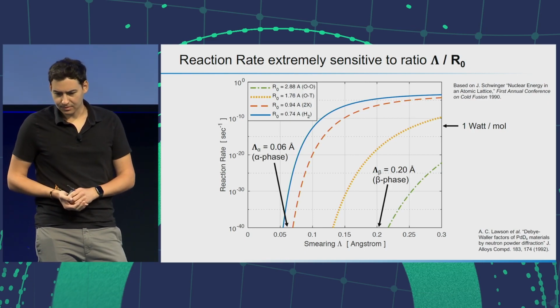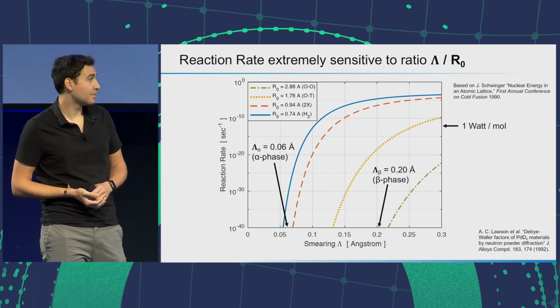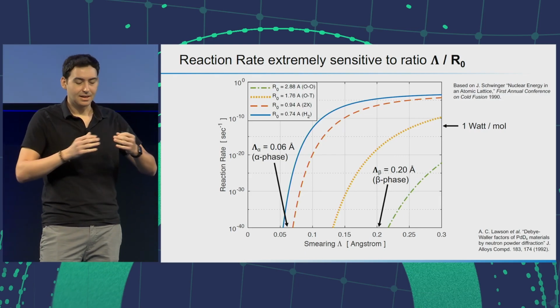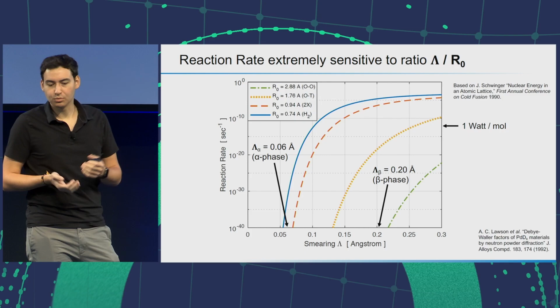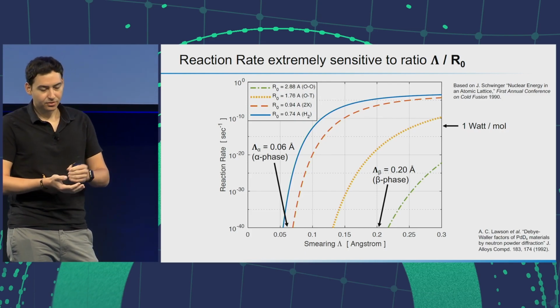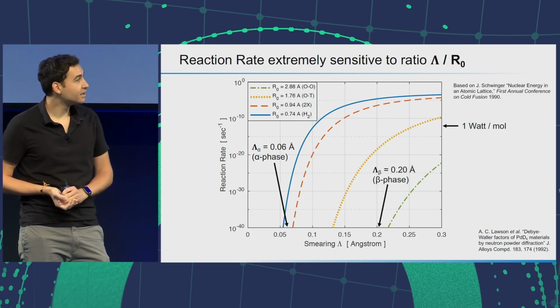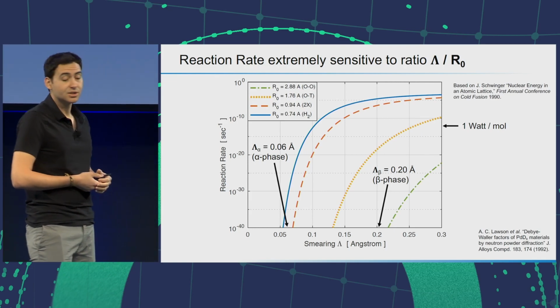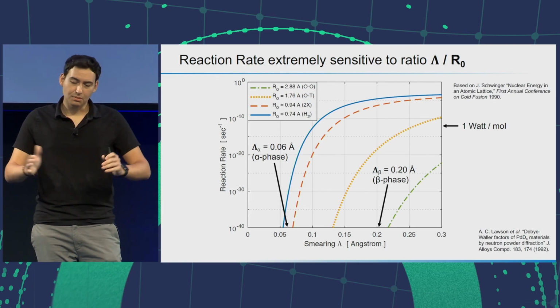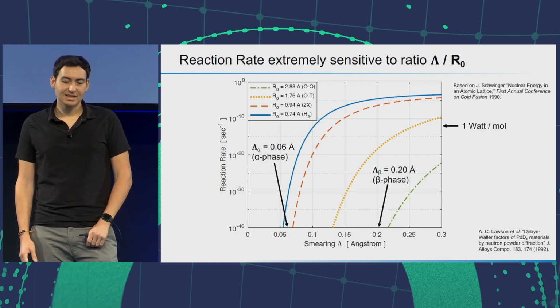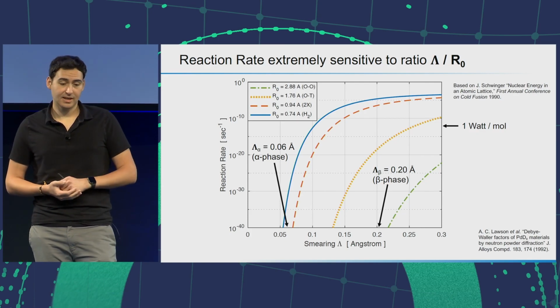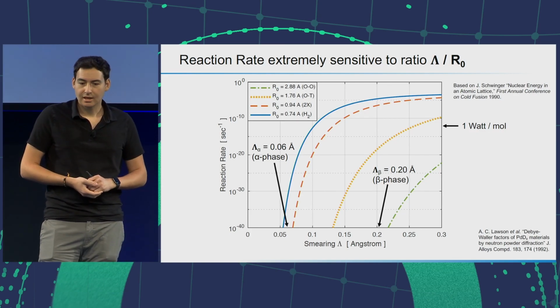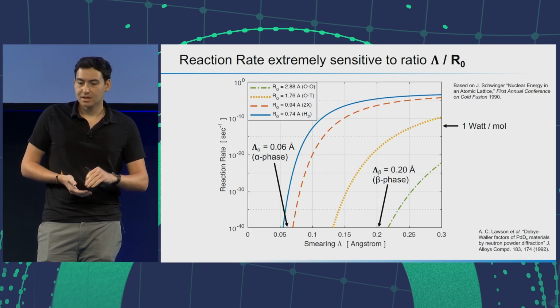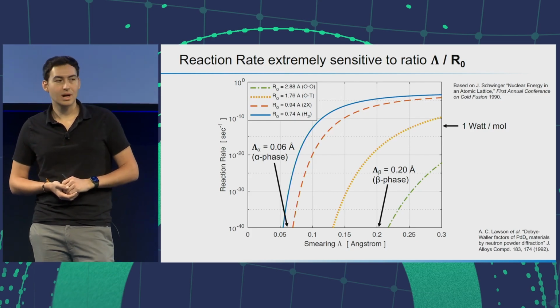I took this from the neutron powder diffraction, the Debye-Waller factor, which tells you how the scattering peak gets broadened, and it gives us a length scale. And so for palladium deuteride, here's the alpha phase and beta phase, 0.06 and 0.2 angstroms. And that's what we're plotting to around 0.3, so say a 50% enhancement of this beta phase lambda. And on the vertical axis, we're plotting another point here, our threshold of 1 watt per mole.